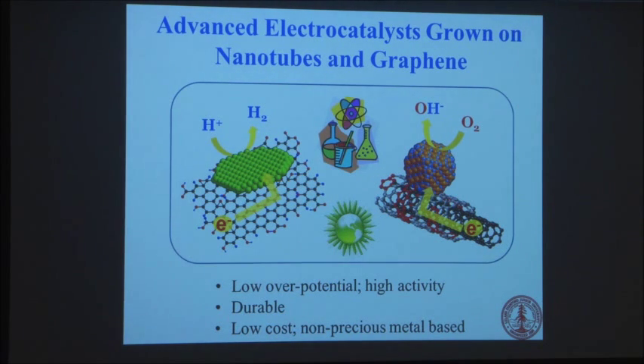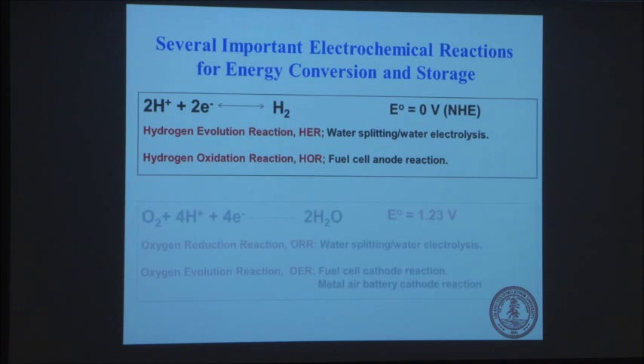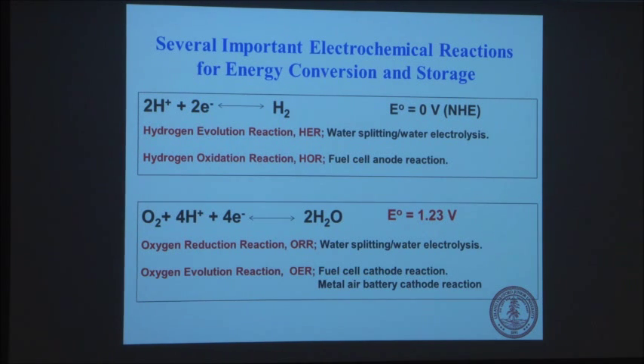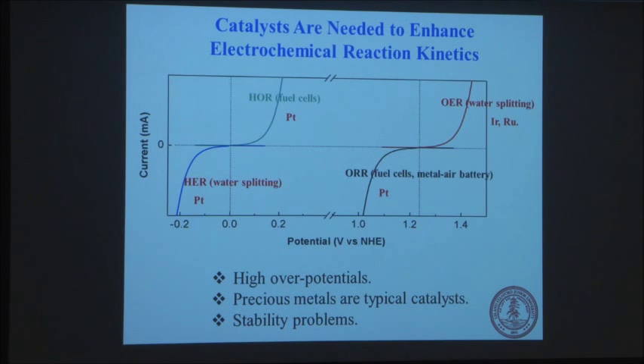All right, I think almost done, but there's one more thing I want to say, which has to do with catalysis. There are these very fundamental reactions, such as evolving hydrogen from water, so it's water splitting, or the reverse reaction, hydrogen oxidation, and oxygen reduction, or water splitting to give you oxygen. These are really important and fundamental reactions that have kinetic barriers that are very difficult to overcome, and you normally don't get much current even if you are above the thermodynamic limit of the voltage.